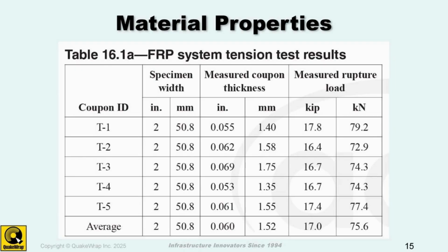So one of the things, for example, is that, for the material properties, if you make these coupons in the field, for example, you do 5 tests here, and get the average of the test, and you see the thicknesses vary a little bit.